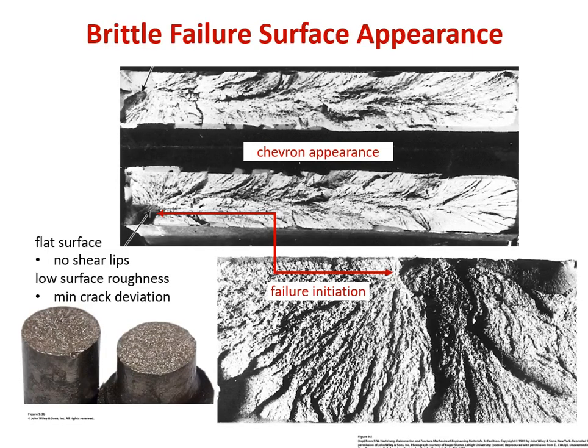So what does brittle failure look like? It's quite a bit different than the appearance of ductile failure. In general, there's much less topography, and quite often fracture surfaces are studied fractally as a quantitative assessment of the amount of energy that's necessary to propagate the cracks across. And so that's actually a way to quantify the topography and relate it to fracture energy.